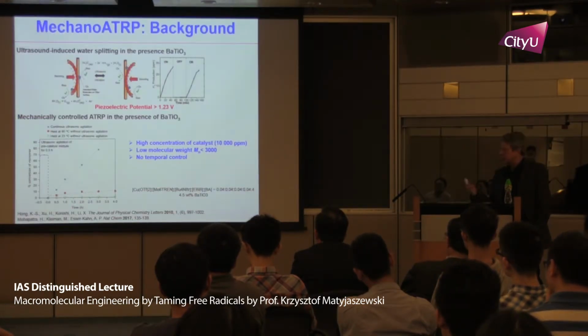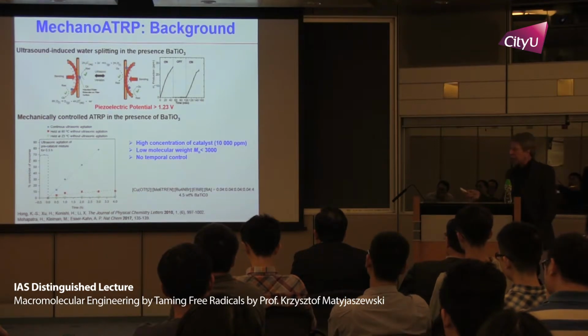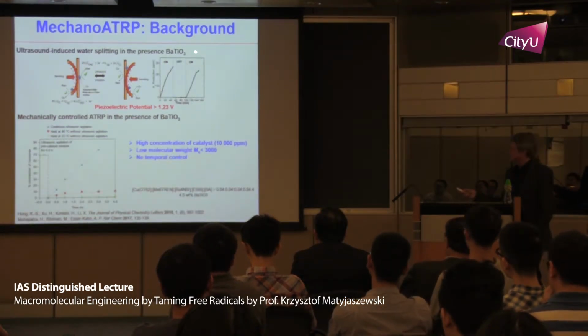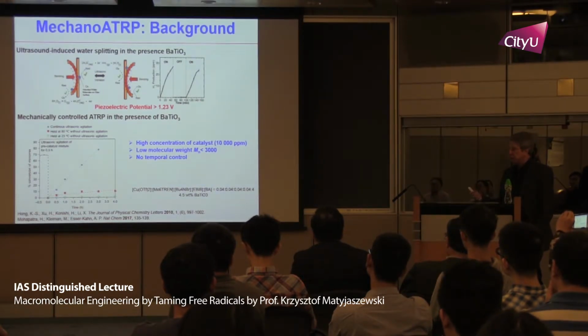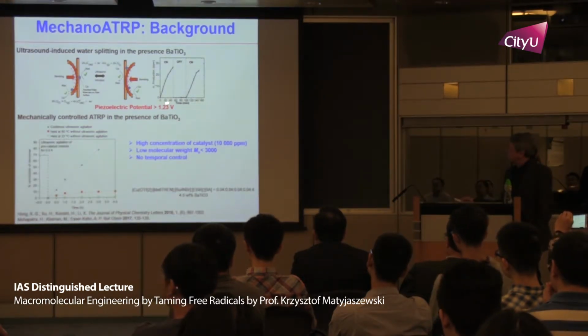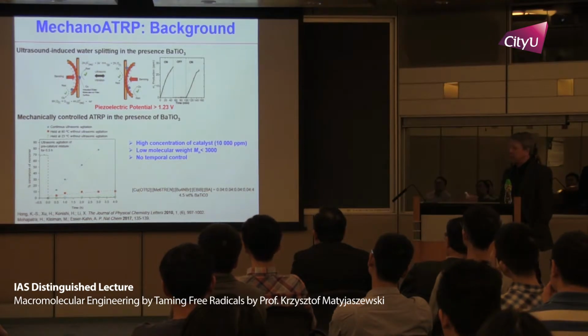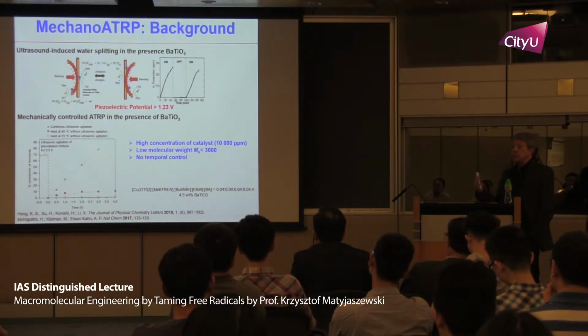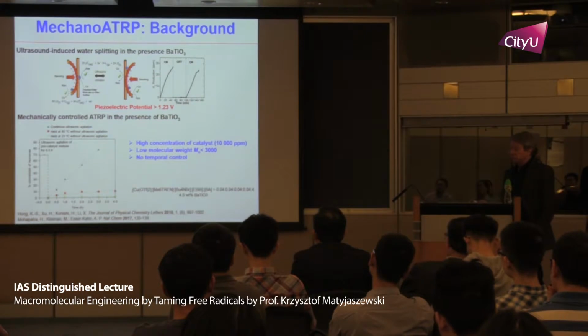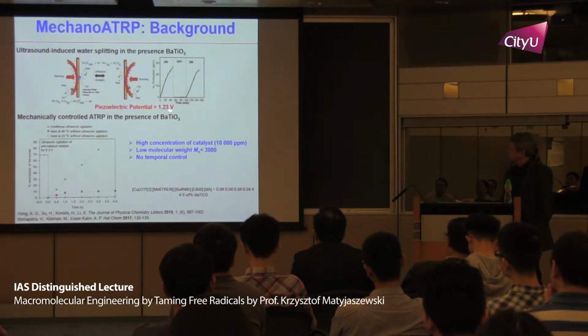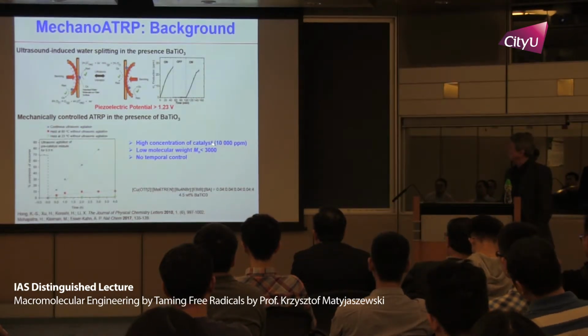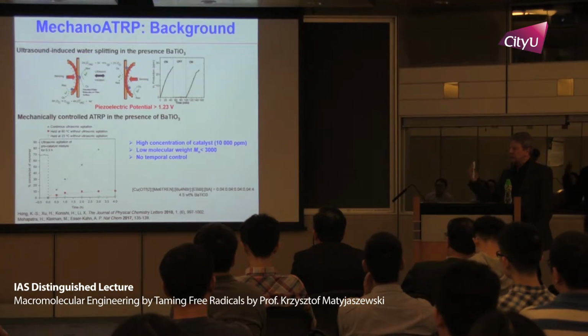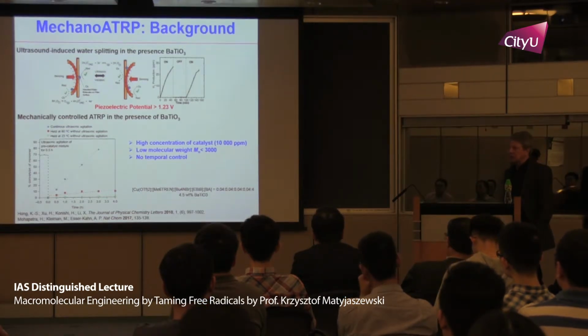So we look really at literature, and if you look at piezoelectric materials like barium titanate under ultrasound forms a potential, piezoelectric potential exceeding 1 volt. So you can split water under these conditions. And there was a paper early last year by using also barium titanate for ATRP, however with a very large amount of the catalyst, around 10,000 ppm, like this old classic ATRP.